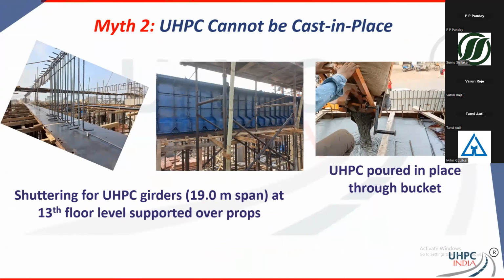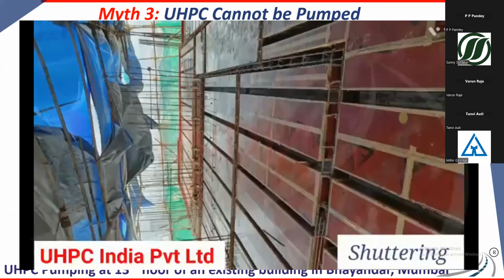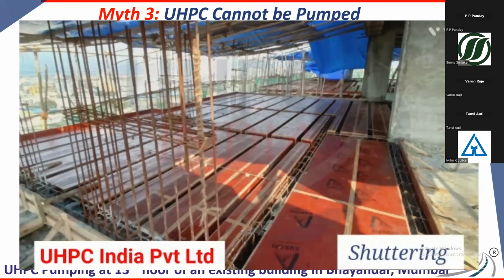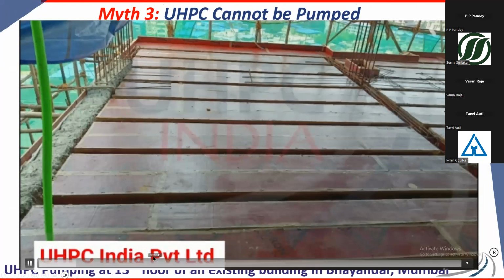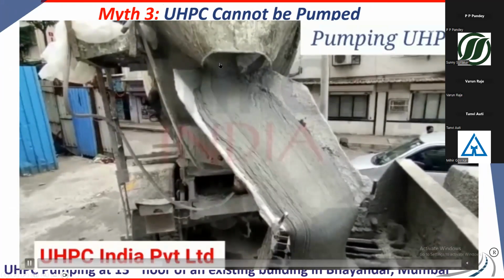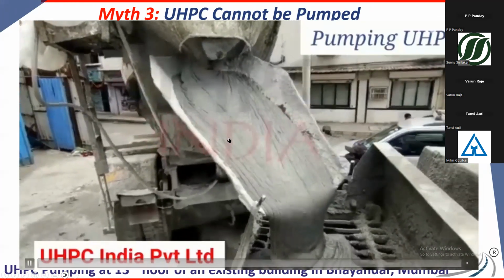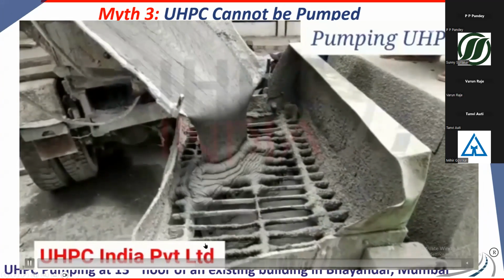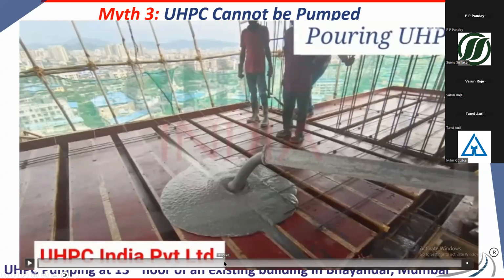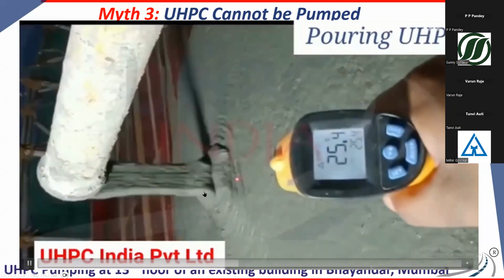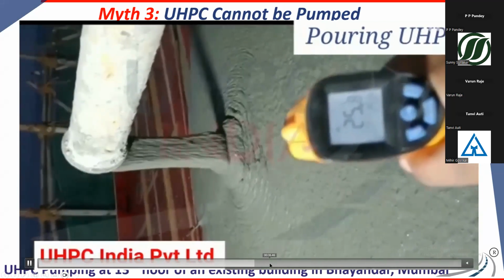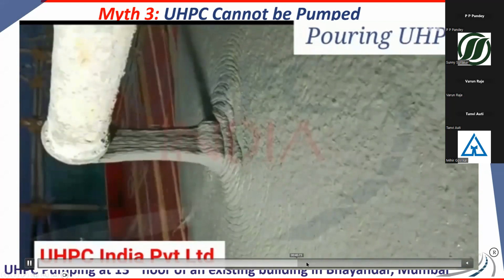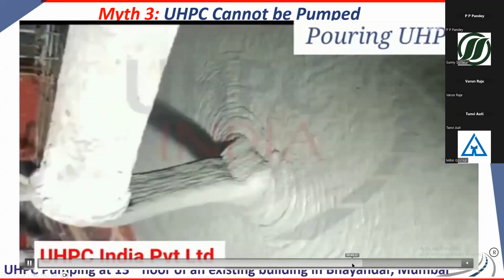It's possible with pre-mixed UHPCs. You can do it at heights. You can cast in place very easily. I don't want to go through this, but this is a pumping video. Let me see if I can move a little further. All the UHPC was made in a transit mixer, not even a heavy duty mixer. In the transit mixer, this was mixed, and you can see UHPC coming out 60 meters high. So it can be easily pumped. That's very nice, no segregation at all.